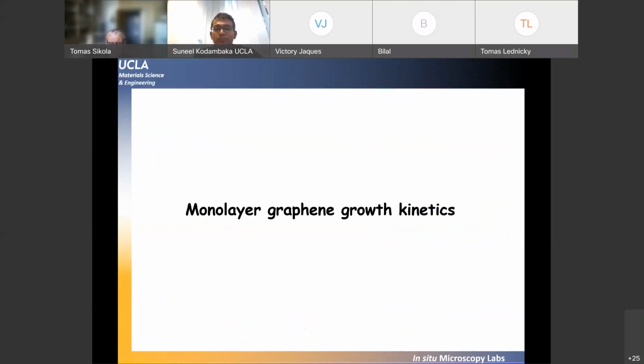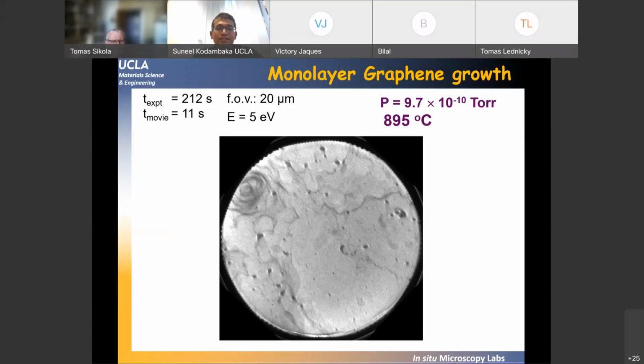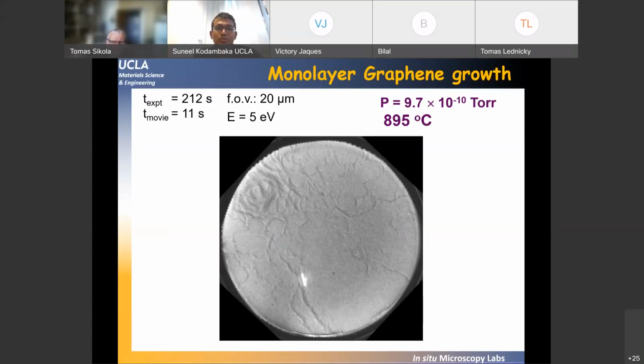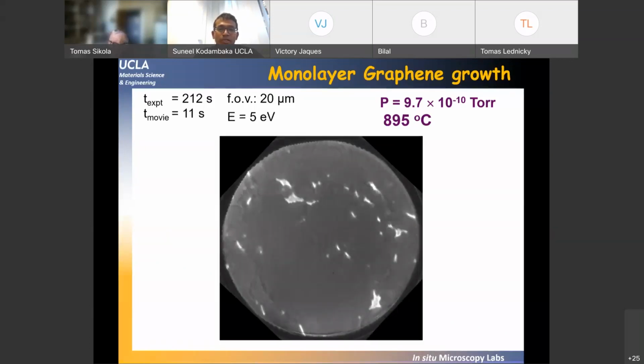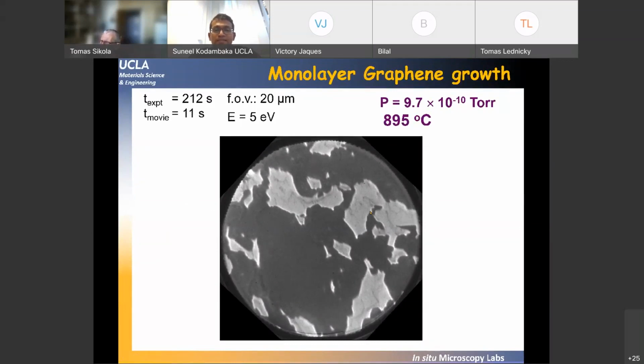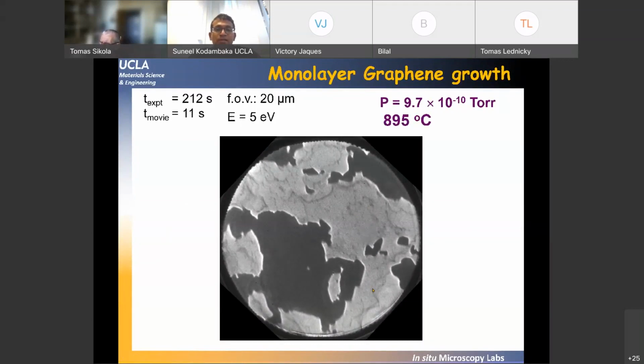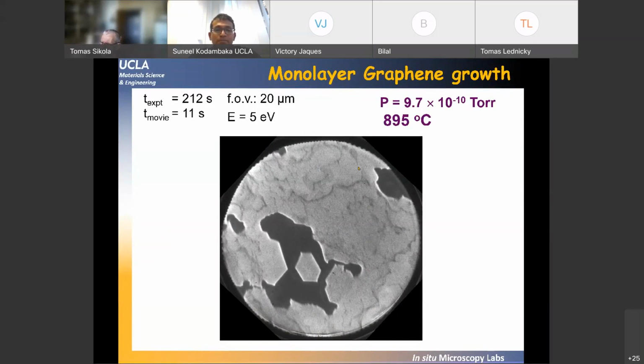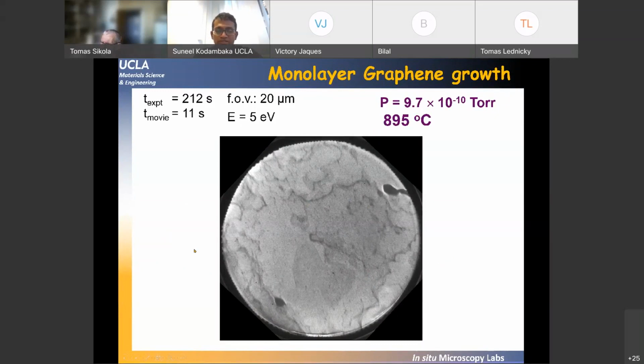Okay, now let me quickly go through the growth kinetics of these graphene layers. Remember, in these experiments, the graphene grows from the bulk. What you're looking at is the monolayer graphene growing as the sample is cooled to some temperature. And again, this is a LEEM movie that's obtained.